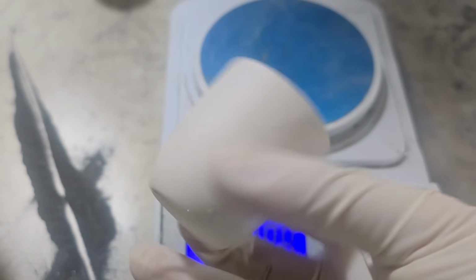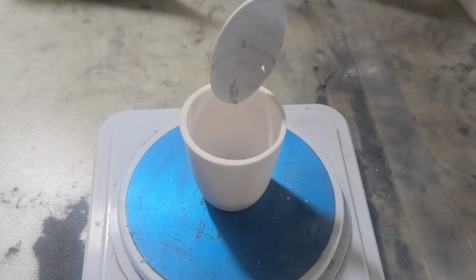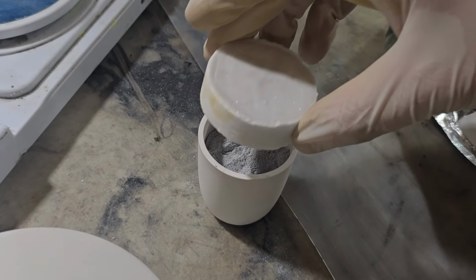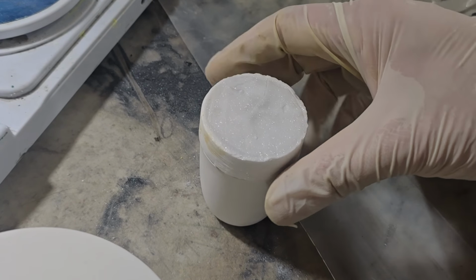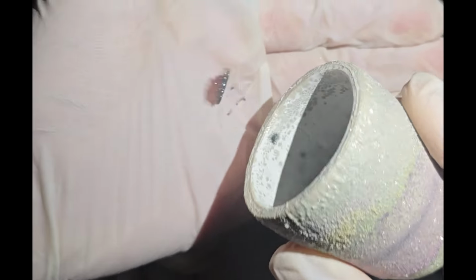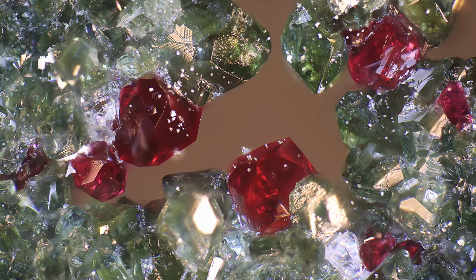I finally settled on zirconia crucibles, a ceramic made from cubic zirconia just like is used to imitate diamond. This stuff is heat resistant and doesn't react with alumina, so even though the flux dissolves it a bit, it shouldn't prevent rubies from forming. And suddenly I had some real success. This one grew a ton of beautiful rubies alongside gorgeous green crystals of cubic zirconia.